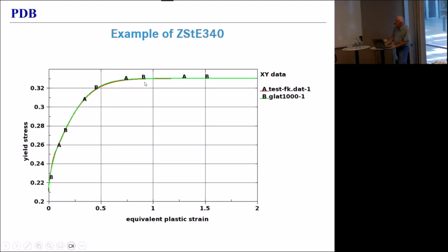One pitfall, you need smooth yield curves. And you need very smooth yield curves. You don't always see that you have a problem. You see 2 yield curves for an HSLA, for a high-strength low alloy steel here. One is, the red one is the original one, the green one is the smoothed one. They look the same on this picture, but they're not.